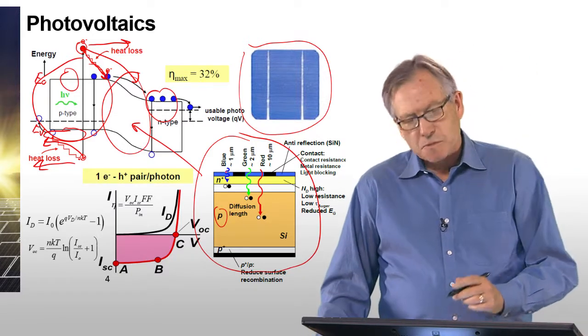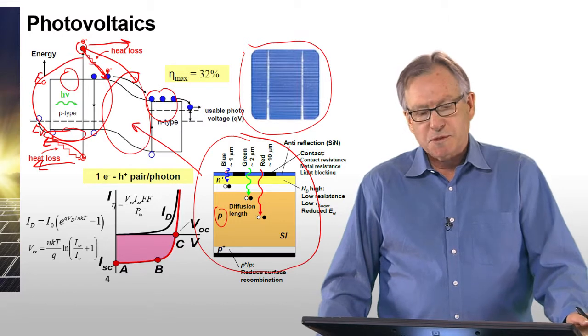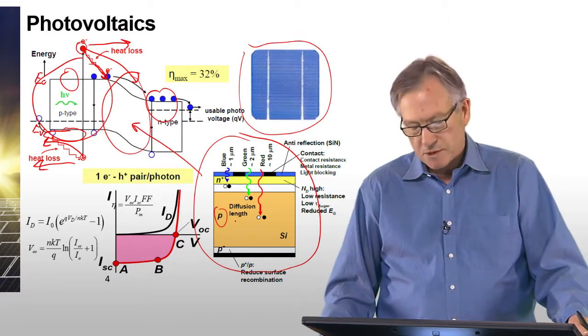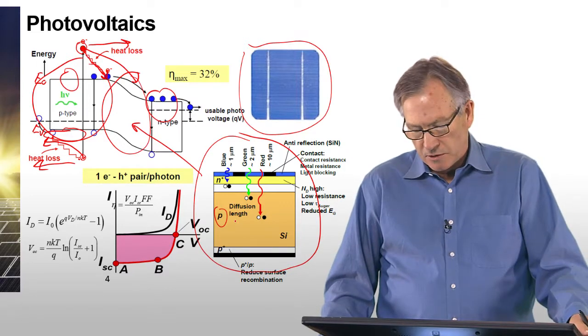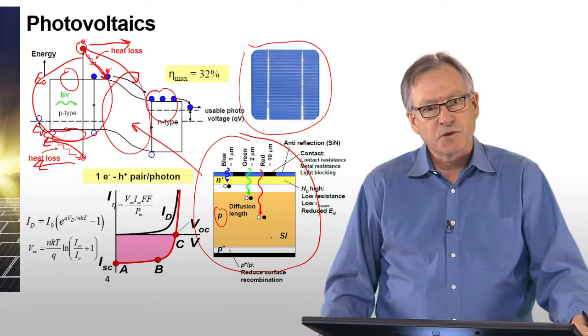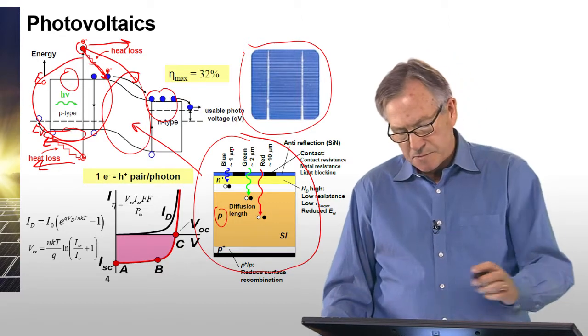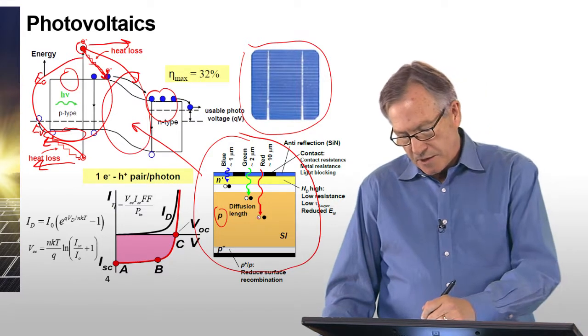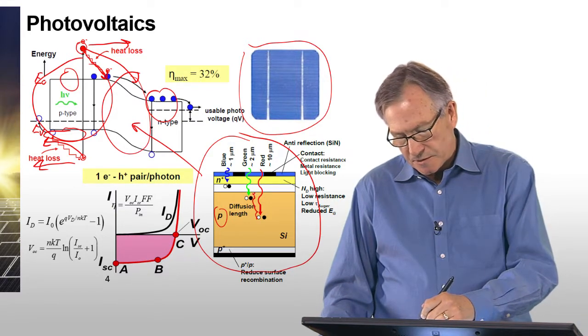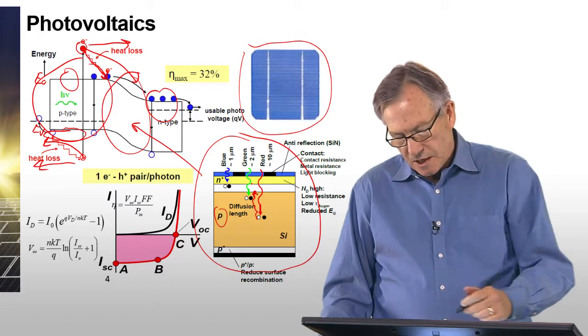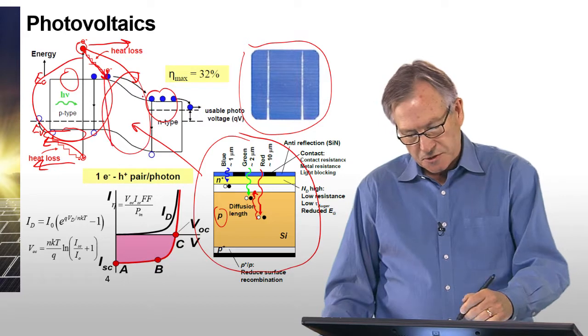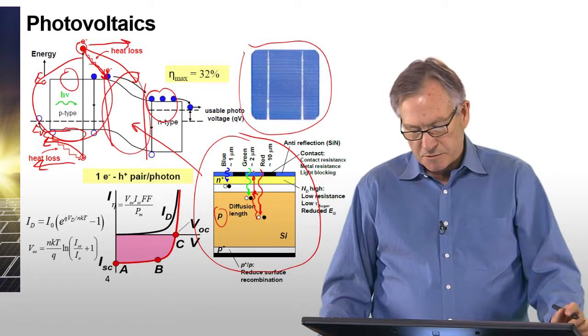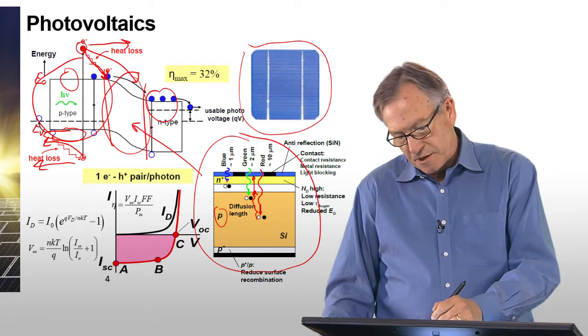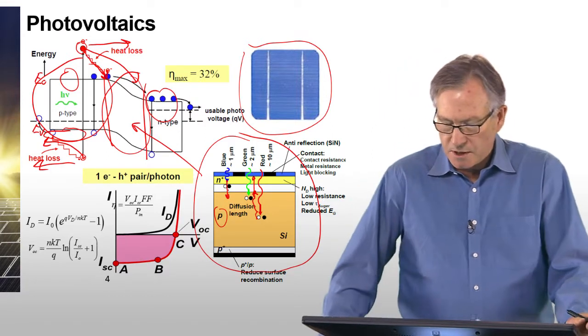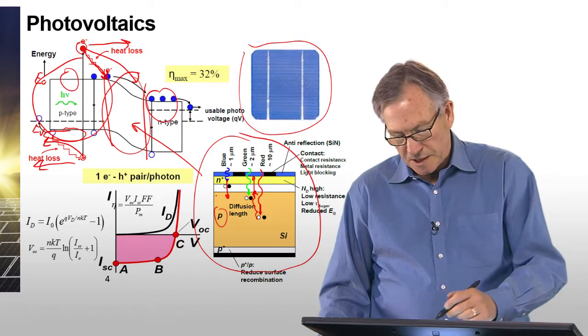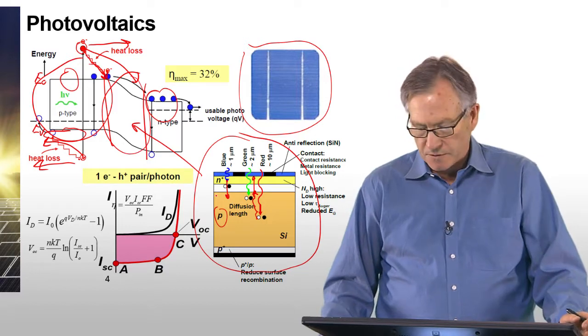And so light is absorbed at different depths because there's a quantity called the absorption coefficient that determines how far light goes in before it's absorbed. Blue light is absorbed very quickly, green light not so quickly, and red light has the furthest penetration. So different colors of light go to different depths within the silicon material. Once they're created, the electron and the hole have to diffuse. The electron diffuses to the edge of what's called the space charge region, which was this region, and is swept across and becomes the photocurrent. Likewise, a hole that's created here is swept across and becomes the photocurrent due to holes. So you have various colors being absorbed at different depths, and that plays an important role in the design of the solar cell.